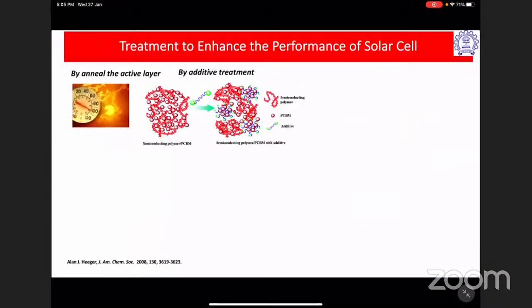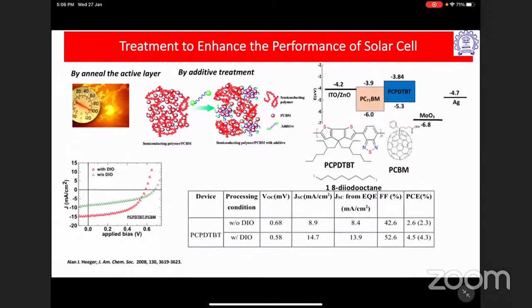There was another thing which Sudipta was telling: by adding some solvent, one can further improve the efficiency of the solar cells, because what you have is very much amorphous nano-mixed regions of the polymer chains and those bucky balls, fullerene balls. But adding a little bit of solvent additive makes you phase pure, with a phase of the fullerenes and a phase of the polymer chains, and that gives rise to much improved efficiencies of the organic solar cells.